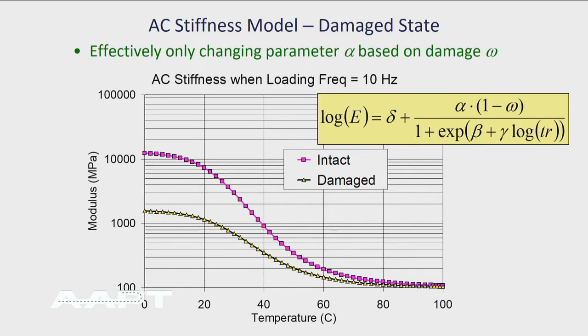What we're damaging actually is the master curve, and this is an actual original intact master curve, and we apply the damage omega to the alpha in the MEPDG stiffness equation, which is what we're using for our master curves, and that basically shifts the master curves down. So every time we put traffic on, we damage that and rotate that down based on the simulation calibration with the damage process, or if it's aging, we're also shifting it up. So the net for each increment is the net of the aging and the damage.